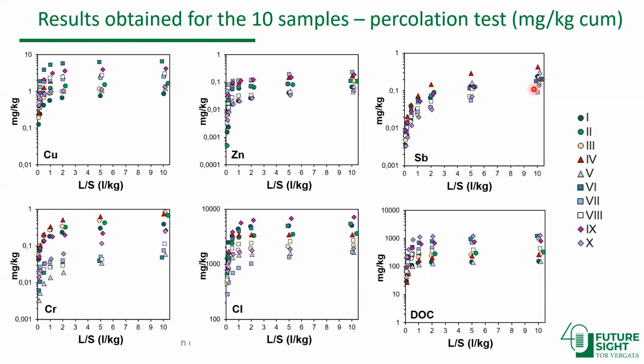Then we can also plot the results of the percolation test as a function of the milligrams of element that are released and accumulated as a function of the liquid to solid ratio. So we see that basically, again, for some elements, samples of plant C, for example, sample 6, show a higher release looking at copper or zinc. And this is interesting because similar profiles are found also for dissolved organic carbon. And we know that typically these elements, these metals, are linked to complex with dissolved organic carbon.